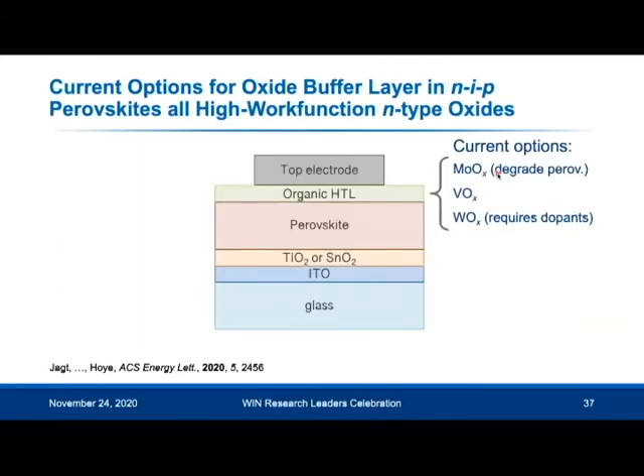So currently, people use high work function N-type oxides as a buffer layer. In particular, people use molybdenum oxide, which is grown by thermal evaporation. But a problem with this is that it reacts with the perovskite and it causes degradation. So even if you encapsulate your perovskite device, you can't guarantee that eventually you won't have some molybdenum oxide reacting with the perovskite through the organic charge transport layer and causing accelerated degradation.